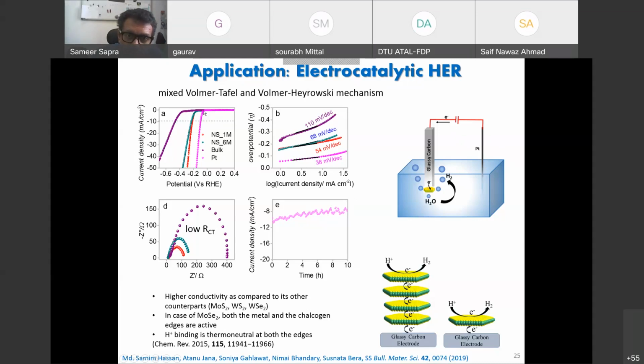You take platinum over here, instead of glassy carbon. And then what will happen is that you should essentially get, without any potential, hydrogen evolution because for platinum, this is a normal hydrogen electrode in that case, right? And for platinum, it's 0 volts conversion of H plus to H2 or the other way around. But because of all non-idealities and the way we fabricate the device, we get about 100 millivolts. Well, everything is reported at minus 10 milliamperes per centimeter square of the surface of your electrode. Okay, so we get about 100 millivolts.